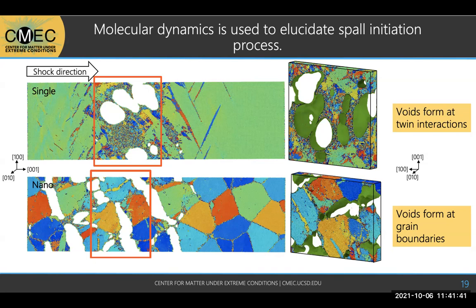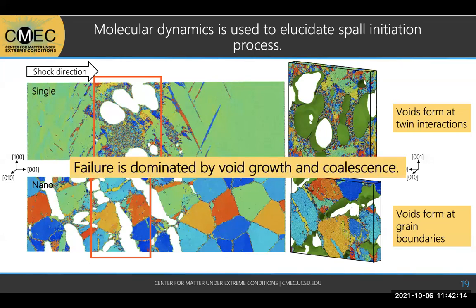During that reflected shock in the single crystal, these twins start forming, and you can see those in that top image there. We find that the voids are actually nucleating preferentially at twin interactions, because those are going to be a lot more energy. And then in the nanocrystalline, you can pretty clearly see that those cracks are opening right between grains. Overall, failure is in fact dominated by void growth and coalescence. Next slide.